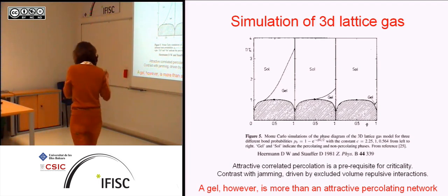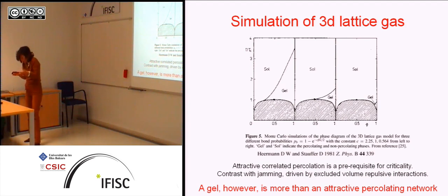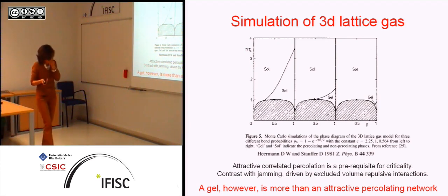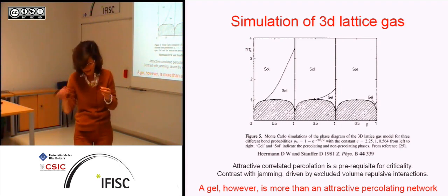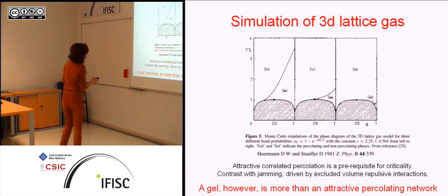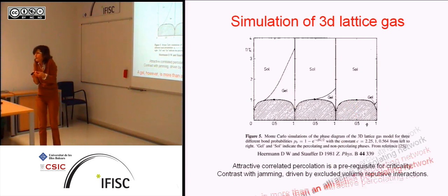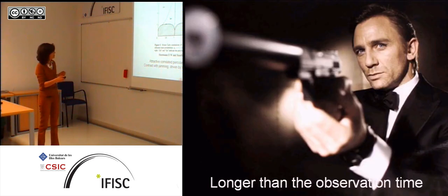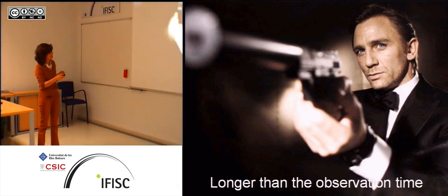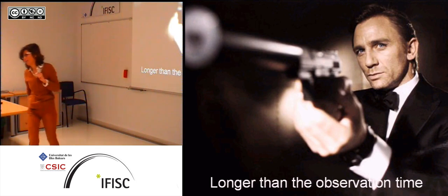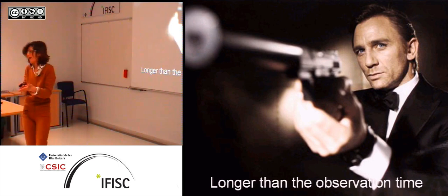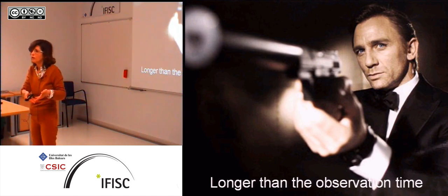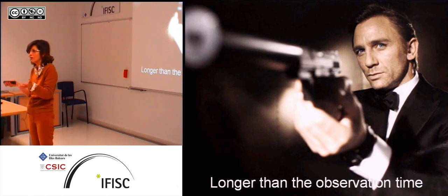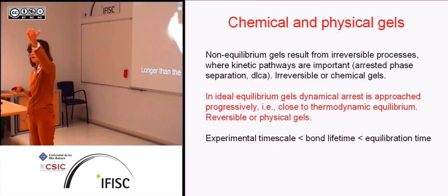And this is where time will play a role, because to have a gel, the way we know it, to have a property whose viscosity diverges or that reacts elastically to external fields, it requires at least that the bond lifetimes have to satisfy certain properties. Okay, so the bond lifetime is an important question, and it has to be longer than the observation time. So, if in an Ising model you find these clusters, but the bonds form and reform so quickly it doesn't affect anything, you don't have a gel. You can have these clusters, you can say they percolate, but you cannot measure them in any property because the bonds are very fast. They don't really live for long enough. Okay? So, how do you increase the bond lifetime? It's really the bond lifetime is the energy of bonding divided by kT.